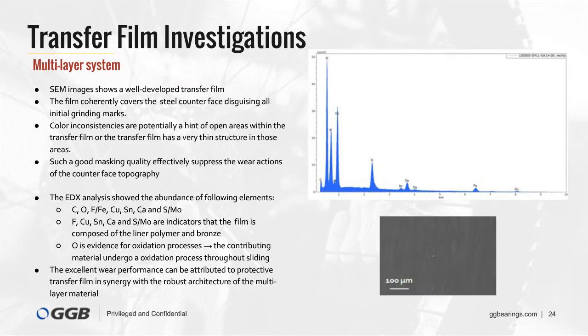On this slide, I would like to show you the transfer film investigations we did on the multi-layer material. The SEM image of the counterface shows a well-developed transfer film. The transfer film coherently covers the counterface, disguising all the initial grinding marks. We can't see any grinding marks that were present before. Only minor areas of the original metallic surface are still present - these are the light areas. This covering of the protruding roughness peaks effectively reduces the abrasive wear actions into low wear.